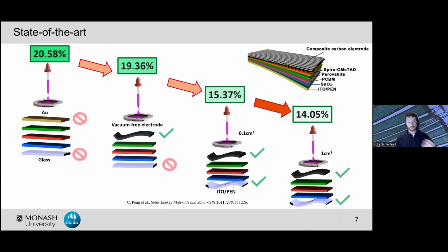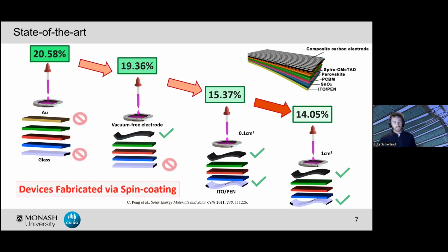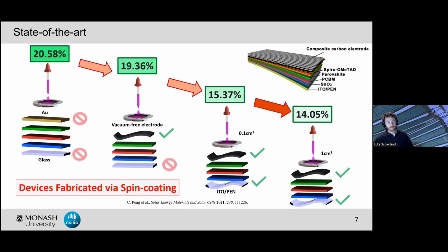so this was a composite carbon electrode, still able to retain the efficiency actually really well, in this case 19.36%, but then by moving to a flexible substrate and then finally upscaling this to a 1 centimeter squared active area device, we again see this dramatic drop in the power conversion efficiency. And so in this case as well, these devices were fabricated via spin coating.